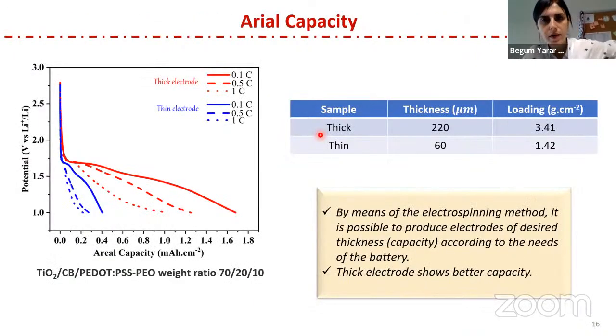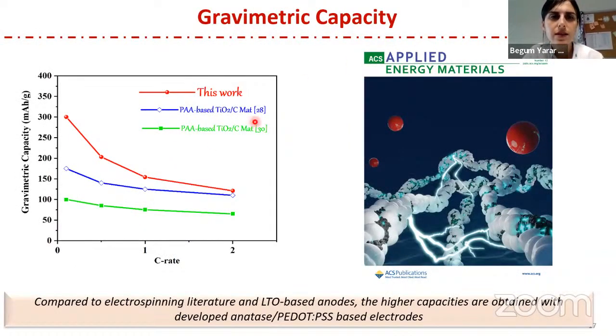And then we perform capacity tests and electrochemical tests. As you can see here, by means of the electrospinning method, it's possible to produce electrodes of desired thickness or capacity according to the needs of your battery. And as you can see here, thick electrodes show better lithium-ion battery capacity. Also, as you can see here, the gravimetric capacity results compared to literature and LTO-based anodes. Here in our work, we obtain very promising and better gravimetric capacity, and we published this study in ACS Applied Energy Materials, and it was selected as a cover image.